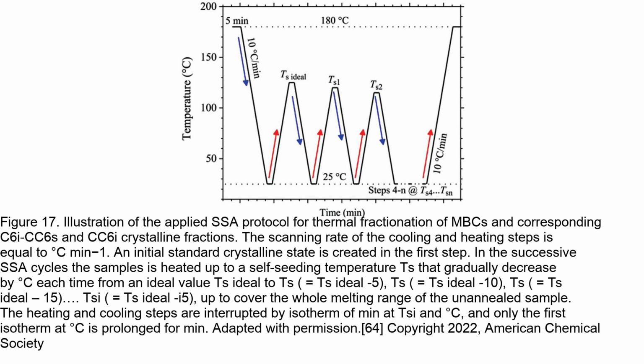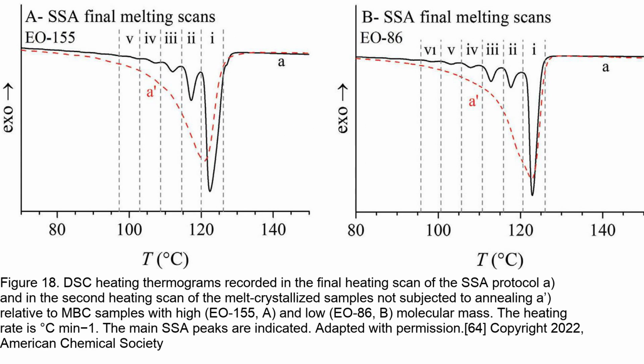Figure 18. The DSC heating thermograms of MBC samples with high, EO155, and low, EO86, molecular mass, obtained by cooling the melt at 10 degrees Celsius per minute from the melt. The thermograms show the different solid-state morphologies that develop based on the molecular mass of the MBC.